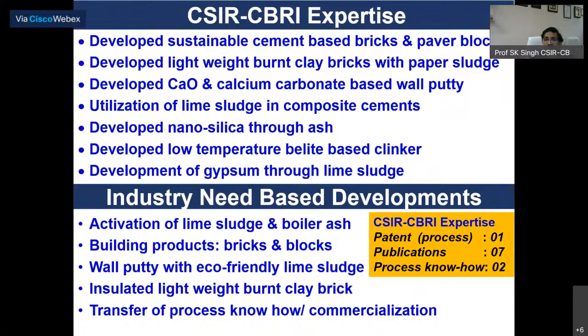We have developed cement-based bricks and paver blocks. We have lightweight burnt clay bricks utilizing de-inking paper sludge. One is calcium oxide based, meaning calcining and then using it as eco-friendly wall putty, and also calcium carbonate as a filler. You know that all wall putties are produced using dolomite. In place of dolomite, we have used more than 80% of this material. And we have also tried, at a small level, composite cement, where we have gone up to 25% using lime sludge.